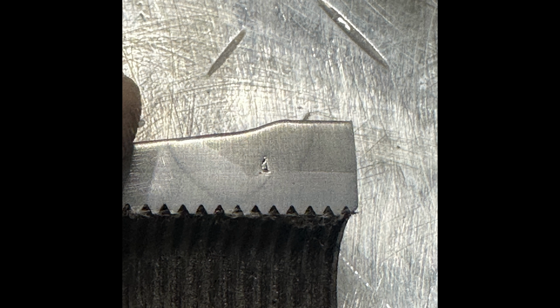From a functional strength standpoint, I believe that this would not break even if you really hammered on this Heim joint, this rod end, quite a bit. But compared to like that 1/8 inch 7018, this is an inferior weld. I don't believe that this defect extended the whole length of the weld. It's probably in a small 1/8 inch section or so, but again, defects are things you don't want.